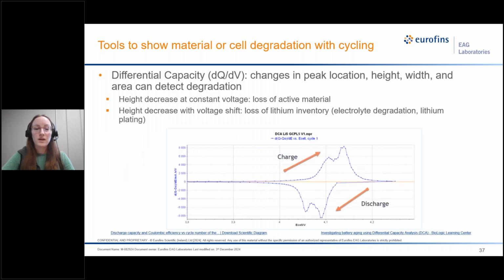And another way to look into our cycling data is through differential capacity. So this is when we would apply a low C rate, and so we can visualize our peaks in the charge and discharge. And when a cell begins to degrade, we would begin to see changes in peak location, height, width, and area. So such as, when we see a height decrease at constant voltage, we would begin to see a loss of active material, or a height decrease with voltage shift, we would tend to see loss of lithium inventory, such as electrolyte degradation or lithium plating.